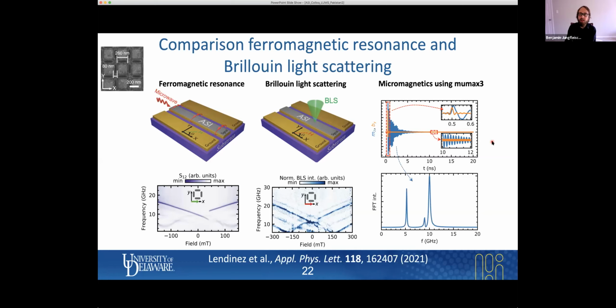We can now take the Fourier transform and see the resonances of the system. So these are the eigenmodes of the system, and we get 3 distinct modes. We can also, just as a sanity check, back Fourier transform the sinc pulse. We see the cutoff frequency of 50 gigahertz. So that's important, that we don't have any drive here above 50 gigahertz, to reduce a spurious signal.